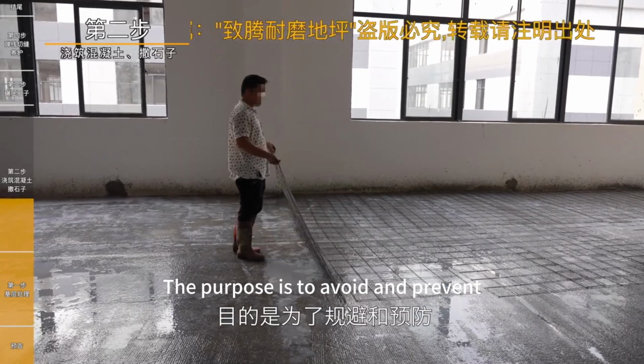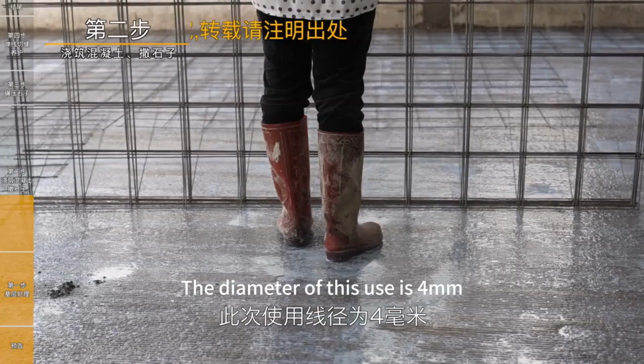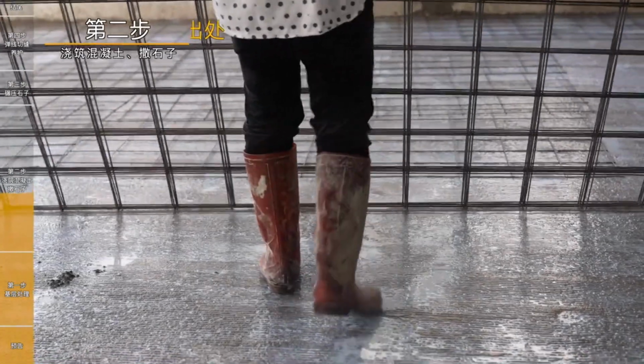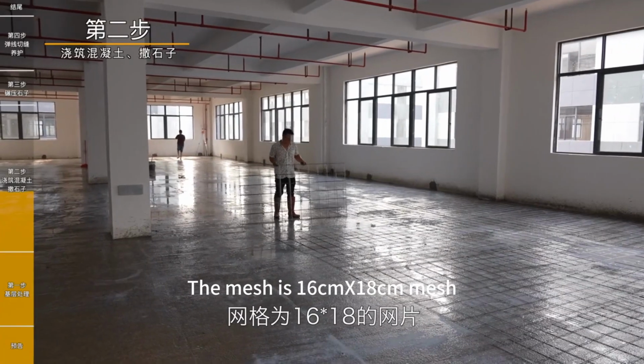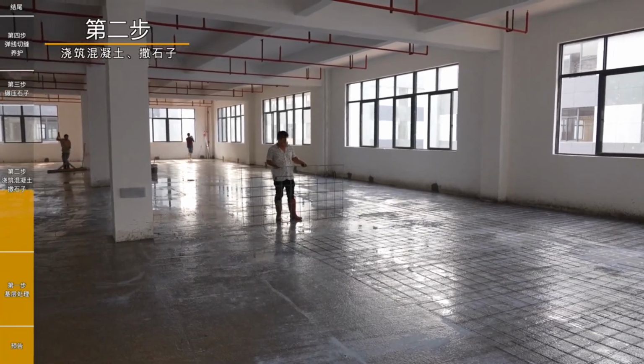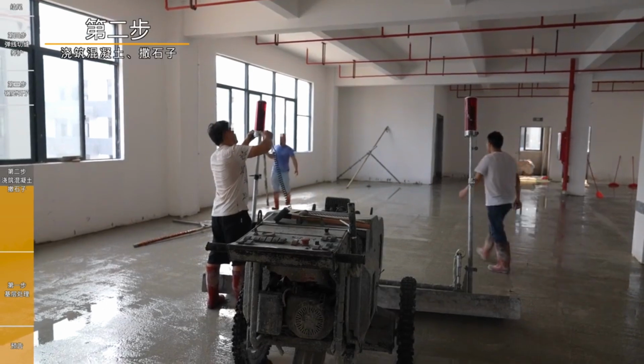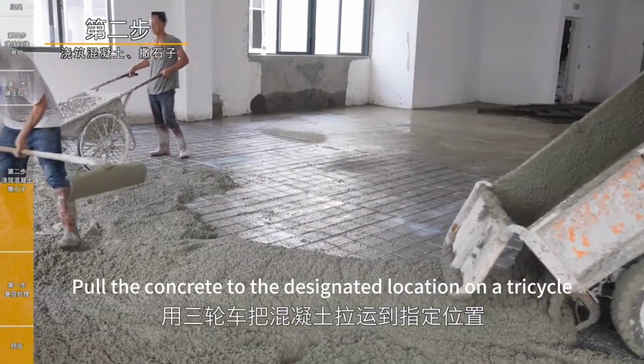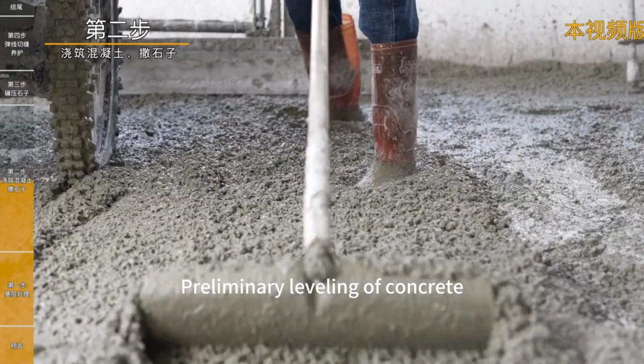Spread the steel mesh on the ground. The purpose is to avoid and prevent the risk of later ground cracking. The diameter used is 4 millimeters, and the mesh is 16 by 18 centimeters. Install the receiver of the laser leveler. Pull the concrete to the designated location for a preliminary leveling of the concrete.